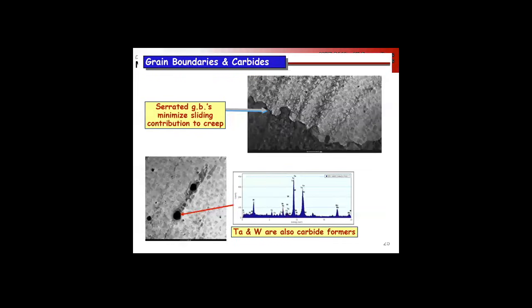And so which do you think is going to resist sliding better - a nice straight grain boundary or this highly tortuous path? And we also have carbides that are going to preferentially segregate to the grain boundary, giving us one.